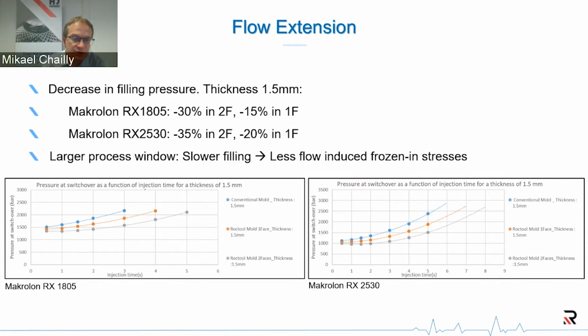Now, if we use Roctool, comparing the two-phase heating with Roctool, we can see that keeping the same pressure limit, this injection time can be increased up to 5 seconds. So you have a significant gain in terms of processing window, and that allows you to have a much slower filling, reducing the number of stresses that are frozen in your materials due to the flow.